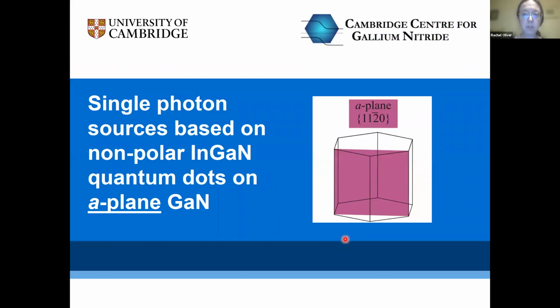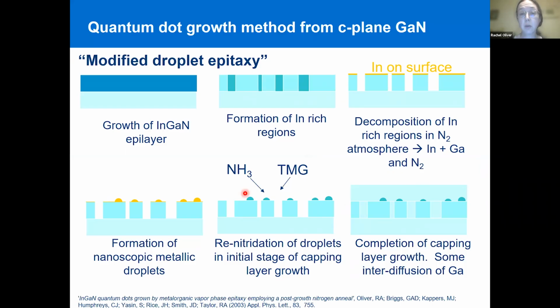Okay, so I've shown you my first c-plane device. We're now going to move on to how we made quantum dot single photon sources based on a-plane indium gallium nitride on this purple plane I've had illustrated for the last few moments. The quantum dot growth method we use in Cambridge is a little unusual. We don't use a classic Stranski-Krastanov growth mode. We don't find it works all that well. Instead, we use something called modified droplet epitaxy.